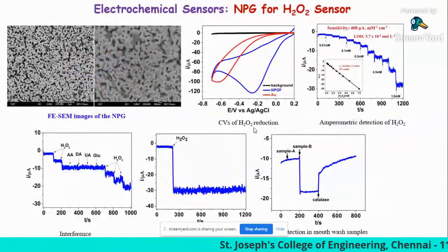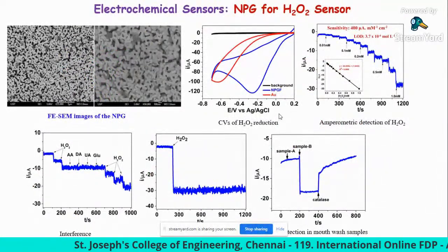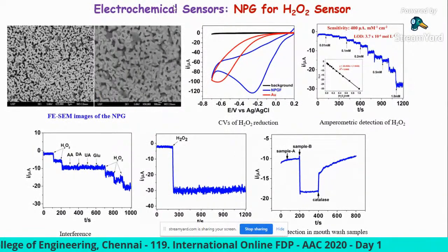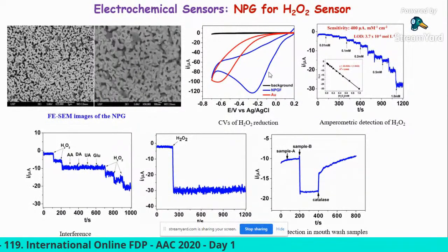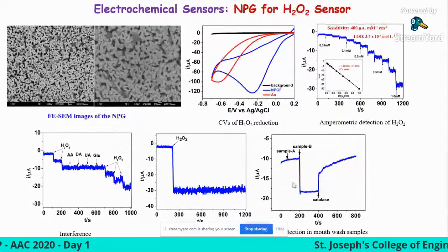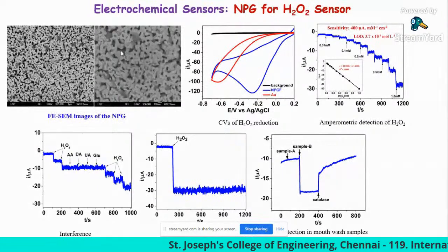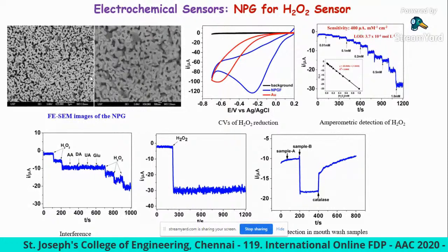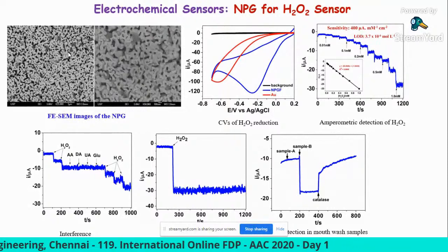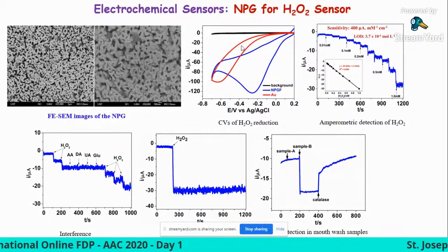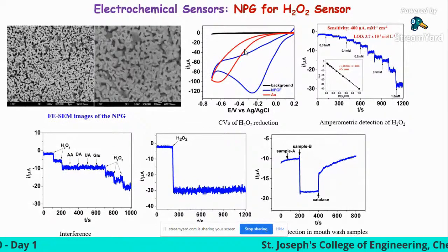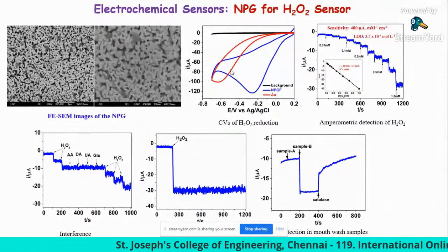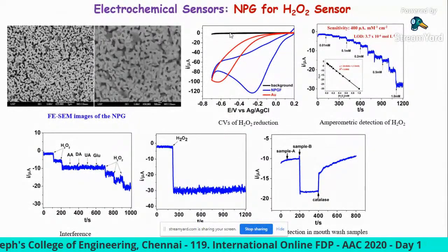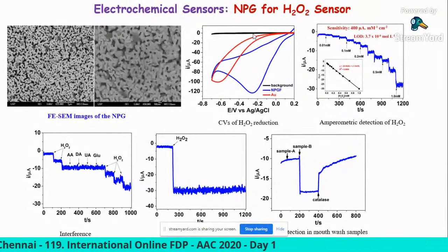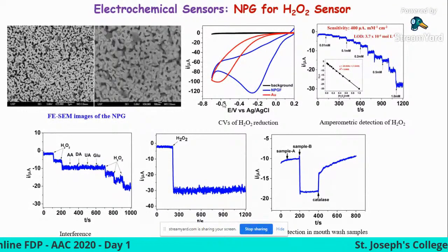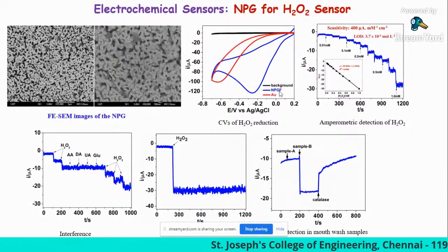Then, in order to extend the electrochemical application, we have developed a sensor for hydrogen peroxide monitoring. This is the scanning electron microscopic images of the fabricated nanoporous gold at 30 minutes anodization time. And this is the cyclic voltammetric responses of hydrogen peroxide reduction for bare gold and the nanoporous gold. This black line is in absence of hydrogen peroxide, and this is in the presence of hydrogen peroxide. Here also you can see there is a clear shift in the peak potential.